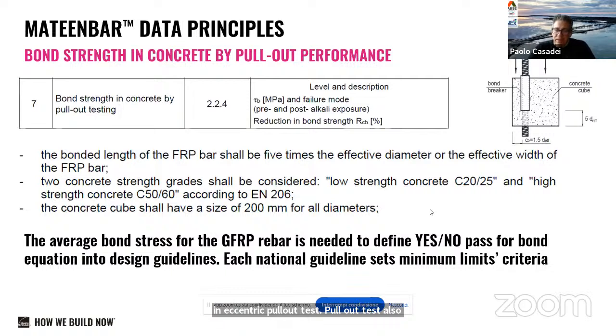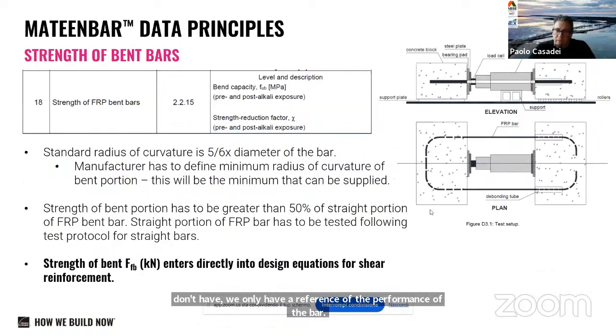And the other very important thing is that this test does provide a level of performance of the bar, but the values that need to be adopted in the design shall not be taken specifically from this test, because with 5 times the diameter, clearly we only have a reference of the performance of the bar, but this value does not really enter into the design.